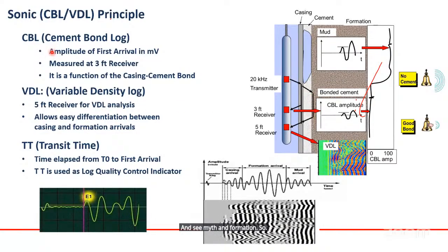So CBL, which is the cement bond log, is the amplitude of the first arrival in millivolts. The amplitude of the first arrival will be recorded. This is the amplitude, it means the height of the wave. So the amplitude of the first arrival in millivolts, measured at 3 feet. It is a function of the casing cement bond. So this is the casing and cement. If it's high amplitude, it means it goes through the casing, so there is no cement. And if it's low amplitude, it means that you have cement behind the casing.